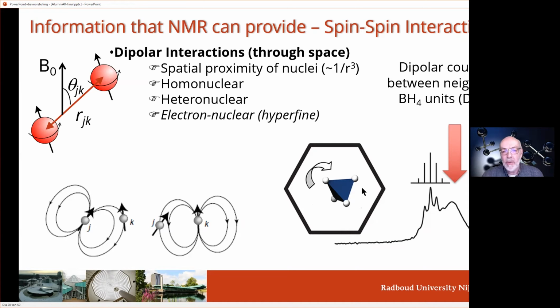Well, in this case, when we look at the BH4 group, what we see is that we have, for lithium boron hydride, this one broad resonance. It's about 7 kilohertz broad, and we calculated the different options for the lithium boron hydride structure. And we found what this means is that in this case, the BH4 units, they are rapidly moving around their own axis. And that means there are no dipolar interactions of boron to their directly bound protons.